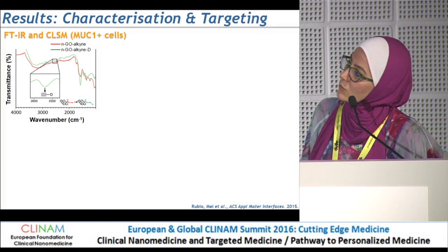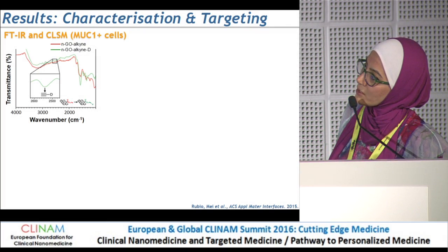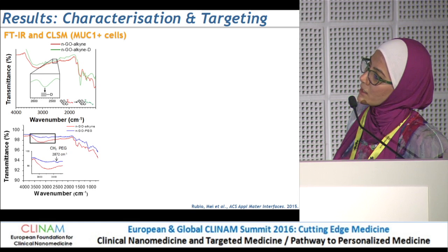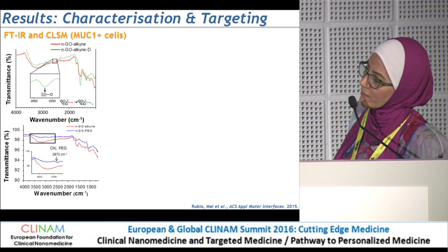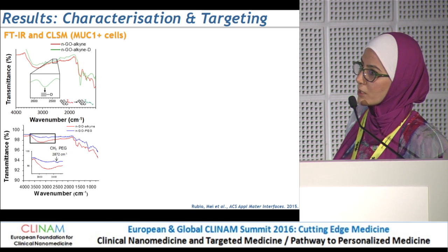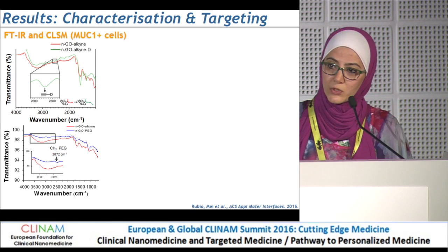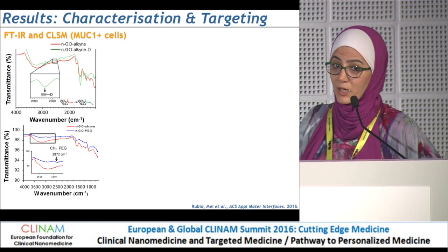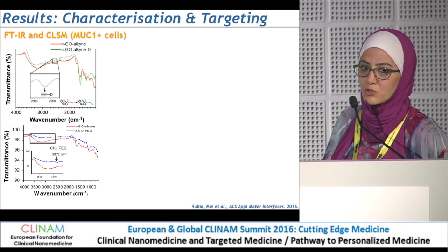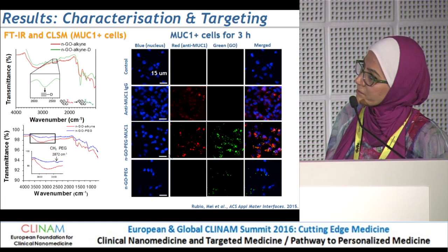After confirmation of the introduction of these functionalities by FTIR, here we use indirect conversion of the alkyne into the deuterium, and then we confirm that we also have the PEG molecule. It's quite important to confirm the introduction of all these molecules because we find in many cases we end up having non-covalent interactions with these macromolecules. They like to adsorb many molecules.